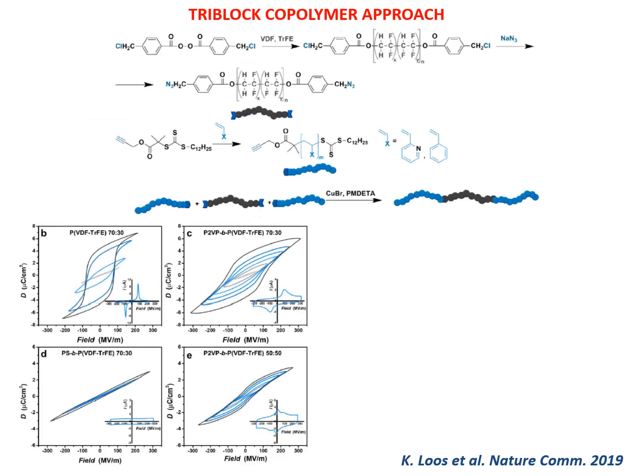The last point I would like to mention is another work of Katja Loos in Groningen. Her group made tri-block copolymers by first polymerization with a peroxydicarbonate, using VDF and trifluoroethylene, then chemical modification of a CH2Cl into an azido group, and then click chemistry onto some alkyne-containing polystyrene or polyvinyl pyridine, showing that such tri-block copolymers are very active because you can have very nice electroactive properties.